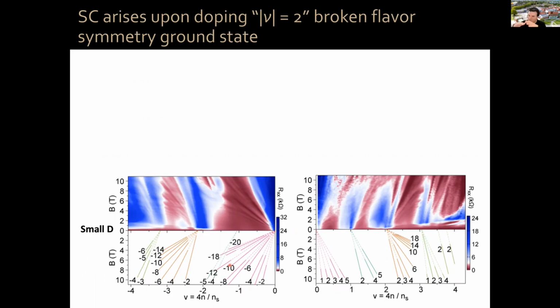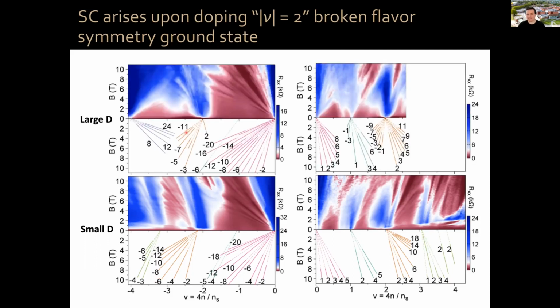You can have 3, 2, or 1 Fermi surfaces, depending on whether you're at nu equals 1, 2, or 3, okay? And that's why the Landau fan diagrams point away from charge neutrality, outwards. Now, at large displacement field, we realize that we have some Landau fan diagrams pointing inwards. And that is key, because if a Landau fan diagram points inwards, it's telling you it's resulting from hole doping of a certain many-body ground state.